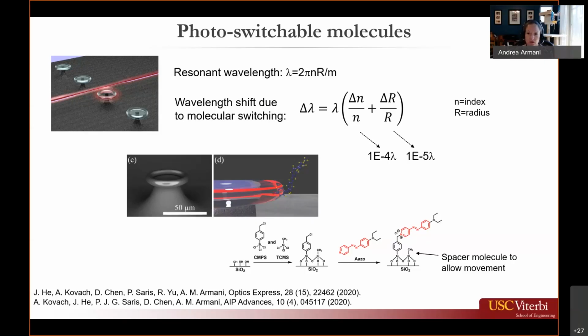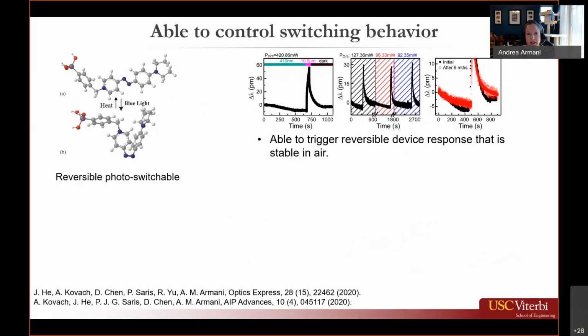Because this is an actual physical change, we can't just attach a single molecule onto the surface. We need to include spacer molecules so that we give this molecule the room it needs to actually perform this folding and unfolding process. So this is the molecular structure. When we shine blue light onto the device, it goes from being this completely planar structure to being a folded structure. And when we expose it to heat, it unfolds again. We did this switching process by exciting the device with a 1550 laser and a blue laser that were simultaneously coupled into the device with a single tapered optical fiber waveguide that we developed and fabricated in our lab that was able to couple in both wavelengths.